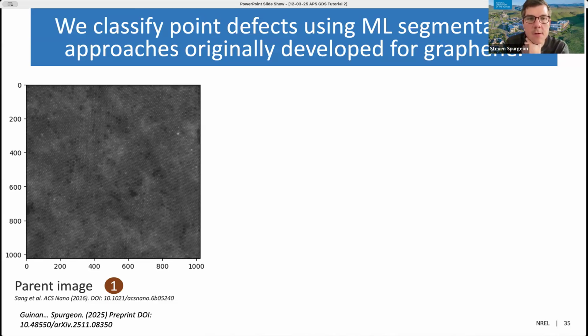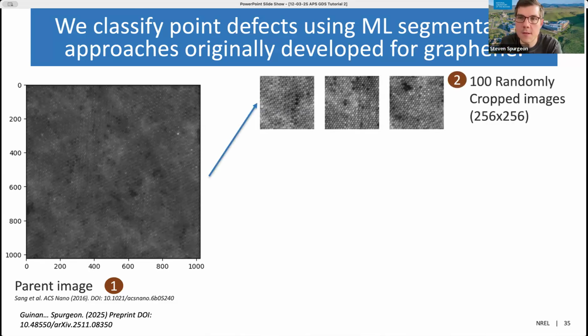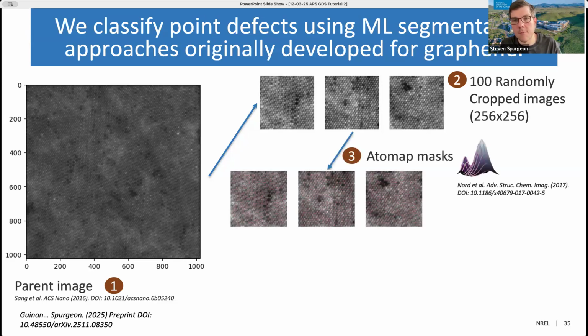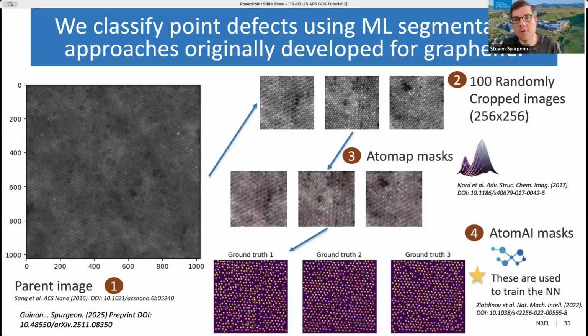The way that we approach this is we take a parent image of the MXene that we have collected, for which we have calculated ground truth masks. And the way we calculate the ground truth is through 2D Gaussian fitting. We take that initial parent image and calculate via 2D Gaussian fitting the atomic coordinates, and then we can randomly crop this image and use it as the basis for training a model. The advantage of the random cropping is that we can take many examples, augment those examples, and provide a relatively decent training set for training a convolutional neural network. We can then derive those masks and provide them as ground truth to train a convolutional neural network to learn to discriminate atomic positions.